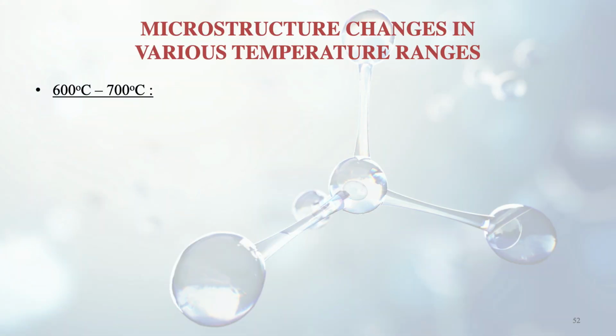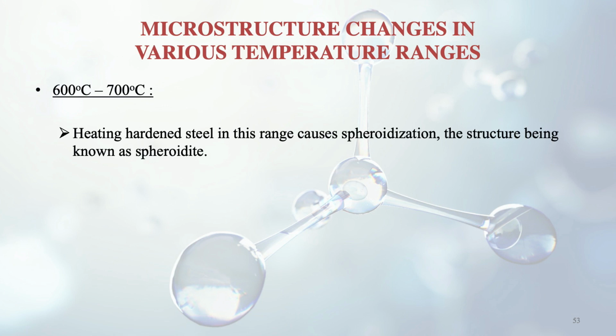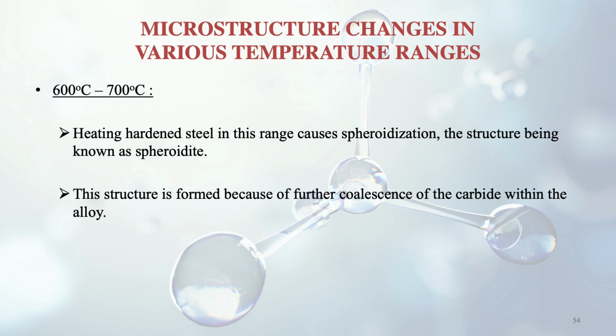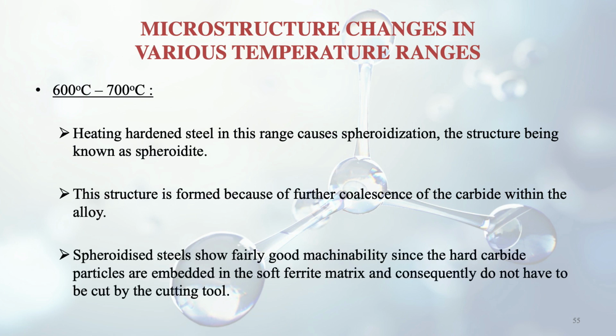Further higher we move up to the 600 to 700 degrees centigrade temperature range. Here heating the hardened steel causes spheroidization. This is a new process, where spheroidization takes place and the structure is known as spheroidite. This structure is formed because of further coalescence of the carbide within the alloy. So there is carbide within the alloy, and when these coalesce, we get spheroidite.